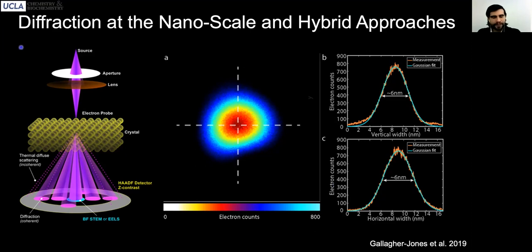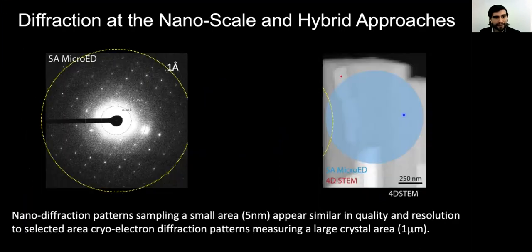This has been recently pioneered. Here you see a focused electron beam that spans no more than about six nanometers in full-width half max. You can see a standard electron diffraction pattern collected from a region of a nanocrystal shown here in blue. The region illuminated by the electron beam canonically is about a micron in diameter, sometimes smaller depending on the aperture used.